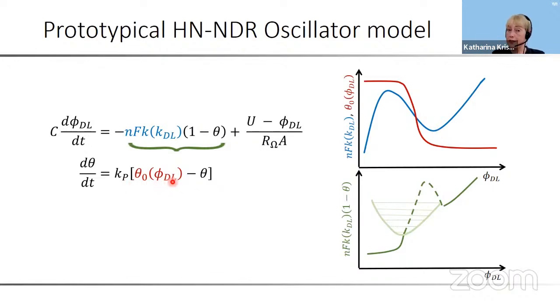But now you have a second species in the electrolyte, which adsorbs on the electrode and has an isotherm that adsorption is high at low overpotentials, but it desorbs at high overpotentials. Now, when you plot the reaction current, which depends on the free area, 1 minus theta, you see that it is inhibited where you have the full coverage of your species, so it's very low down here. And then as the species desorbs, the current increases, and then actually it starts to oscillate around this branch, because this is again our negative feedback variable. And usually you have a hard disappearance of the oscillations with very long periods, which is called a saddle loop bifurcation in nonlinear dynamics.